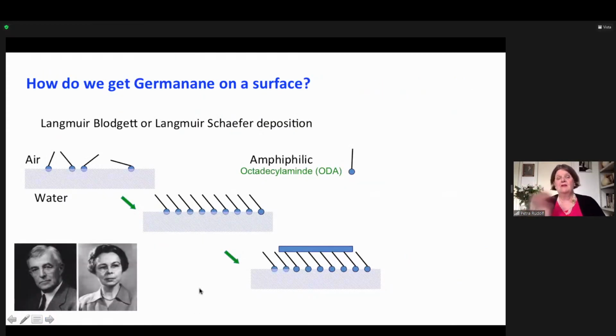How do we put germanane on a surface? Well, we use a very old technique that was invented by Irving Langmuir and Katharine Blodgett. What they did was to put amphiphilic molecules on the water surface, so they will not drown in the water, but they will stay there. Then you can compress them, and then you can come with the substrate and pick up your layer. If you pick it up in this way, it is called the Langmuir-Schaefer method, and Schaefer was a technician in their lab.